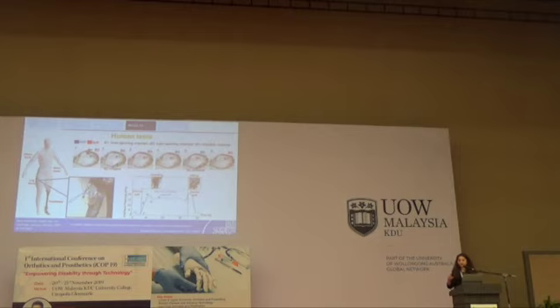By putting a Tekscan pressure sensor between the band and the limb, we tested the system starting from a soft configuration when the subject was standing. Then the system was activated, and you can see in the slide that it resulted in an increment of the pressure applied on the tissues, and so of the fitting of the system.